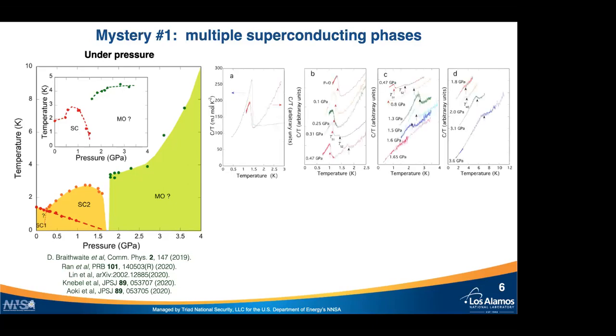And it's important to point out that these measurements were done both with resistivity and AC calorimetry. That's very important because if you have two superconducting states, you have to have a bulk thermodynamic probe to probe both of them. So this is here shown in panel B, for example, at 0.5 GPa, you can see clearly two peaks for the superconducting transition temperatures.